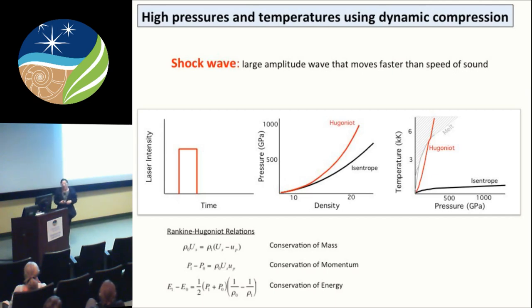A shockwave is a material's response to impacts and explosions — the material's response to a very high amplitude pulse of energy. Giving different materials different pulses maps out what's called a Hugoniot: the locus of states in P-T space corresponding to how the sample responds. This gives us equation of state information. In shock compression, we can determine final density and pressure exactly by solving the Rankine-Hugoniot equations, which allows us to measure a few velocities — shock velocity and particle velocity — and then calculate exactly the pressure and density achieved.